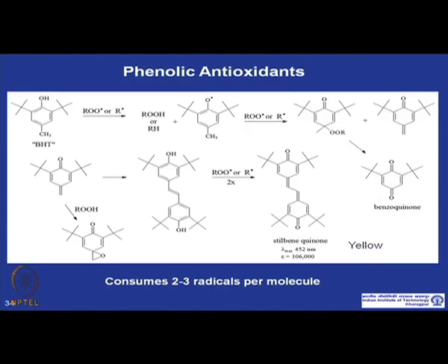So, this is the mechanism by which they work. For example, this additive traps this radical, forms a radical itself, which can rearrange and react with other radicals and form non radical species, and these final species like stilbenequinone or benzoquinone are sometimes color bodies.